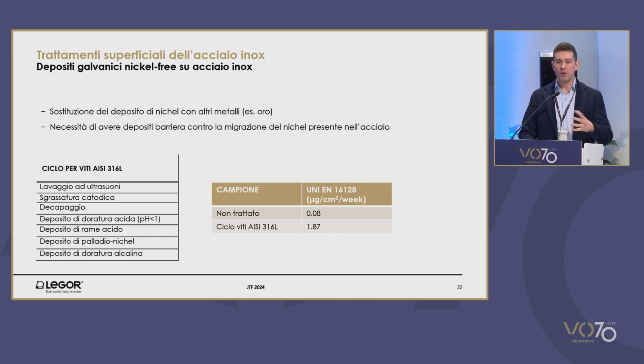Nickel-free cycles for stainless steel objects have been developed. You just have to remove the nickel deposition, usually replacing it with gold deposition. What is difficult is making sure that the anallergic feature is maintained. When you scratch the chromium oxide on the surface, sometimes you also remove the barrier that you have in stainless steel, safeguarding the object from releasing nickel. So by means of nickel-free electrodeposition, you have to remake this barrier effect so as to contain the potential release of nickel.